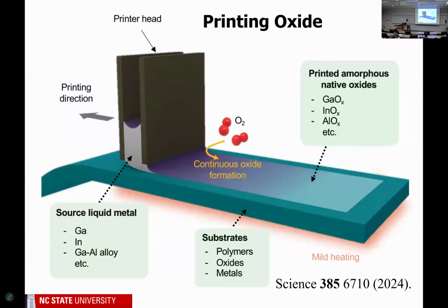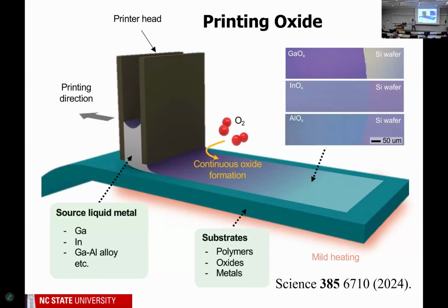So this just kind of summarizes what I've shown you, that we're taking the liquid metal between this little slot, dragging it across, and relying on oxidation to get this to form. And what's quite cool about this is that there's other metals like aluminum. Remember the brother, the sister? It dissolves a little bit into gallium, but aluminum is even more reactive than gallium. And so if you put in 1% aluminum, you can actually deposit aluminum oxide, which is crazy because aluminum melts at like 660 Celsius, and we can deposit it at room temperature.